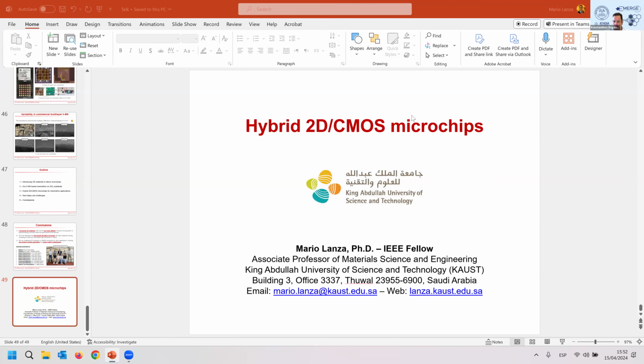Another part of the question is whether you measure any quantum effect while you scale down the thickness, if something is predicted to be observed when you go down to a few nanometers. Yes, we have observed conductance quantization in some devices. We have a paper in npj 2D Materials and Applications. This analysis was done by one of my collaborators, Professor Juan Bautista Roldán from the University of Granada. He observed in some devices the typical jumps between different conductance states, and he made all these fittings. At which temperature? Room temperature. Yeah, room temperature.